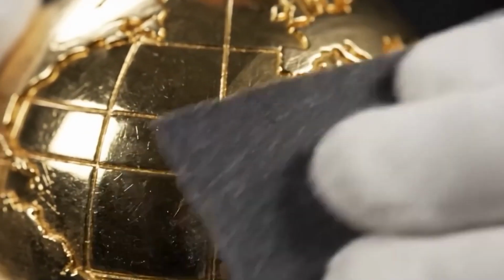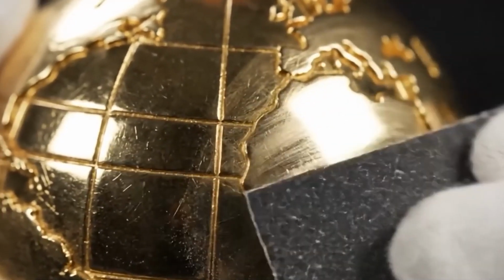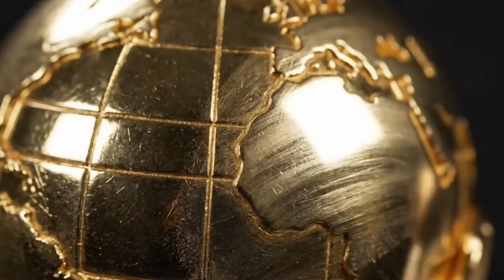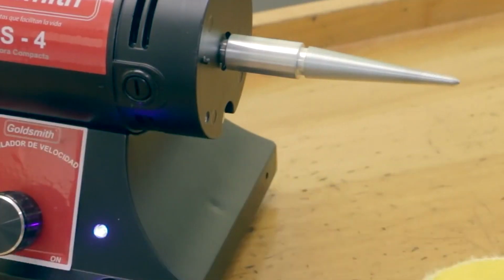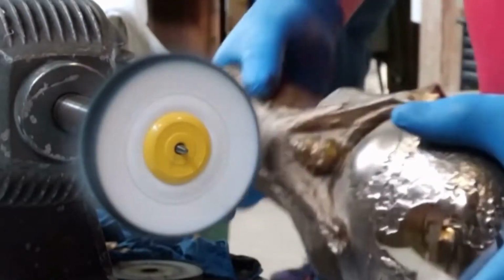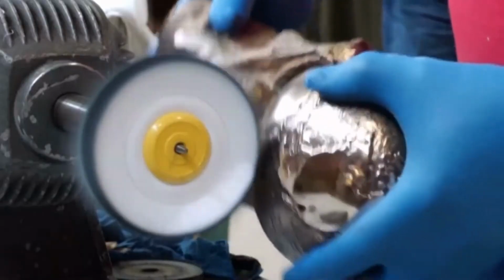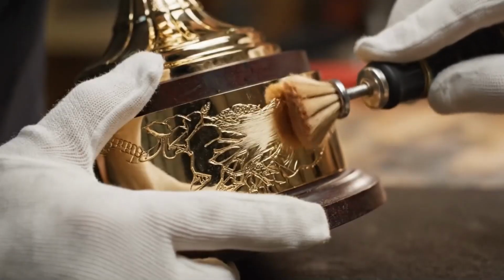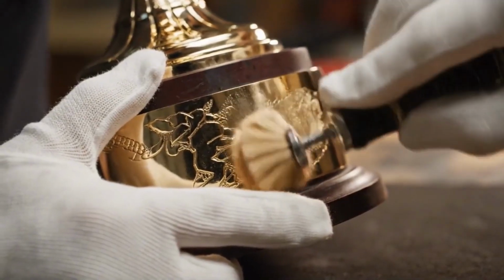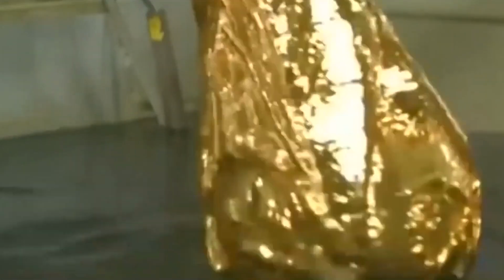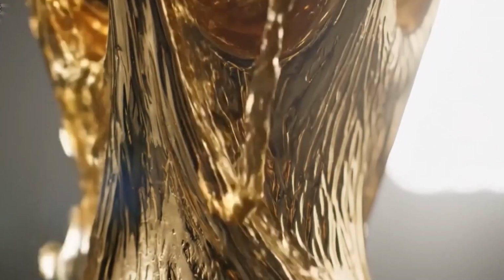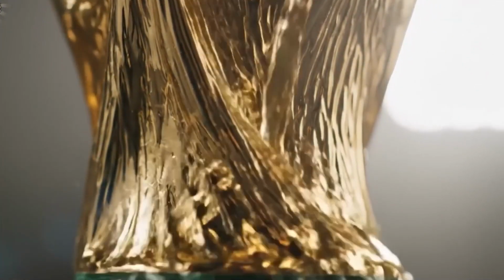Cleaning between stages is essential. A residue of coarse abrasive trapped during fine polishing can scratch the metal. That's why the piece is washed, dried, and inspected repeatedly. Ultrasonic baths, deionized water, filtered air, and drying chambers reduce the risk of staining. Ordinary humidity can leave mineral marks on such a bright surface. Even a fingerprint can lead to grease, dullness, or micro-corrosion if left for too long.